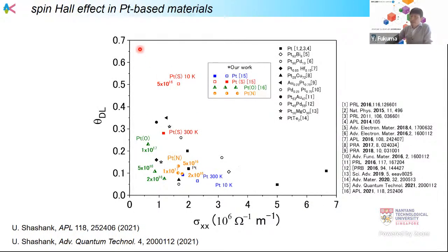But we can also look at this figure again for the spin Hall effect in platinum-based materials. We also made samples with oxygen implantation and nitrogen implantation. With increasing implantation concentration, conductivity decreases, but the spin Hall angle is enhanced. We can see a large enhancement of the spin Hall angle in the sulfur implanted material. If we look here, we can find a material around here at room temperature that could be good for spin orbit torque memory and computing applications.